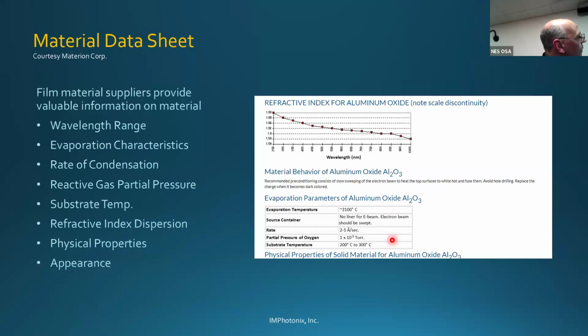Just quickly, this happens to be just one example. This picture here is courtesy of Materion. They supply a lot of the film material that the industry uses. In this case, it's aluminum oxide. As designers, we rely on this data to guide us on how to evaporate something like aluminum oxide. And we look for the wavelength range and evaporation characteristics, substrate temperatures that they recommend that we deposit it on, and what the partial pressures of oxygen we have to use.